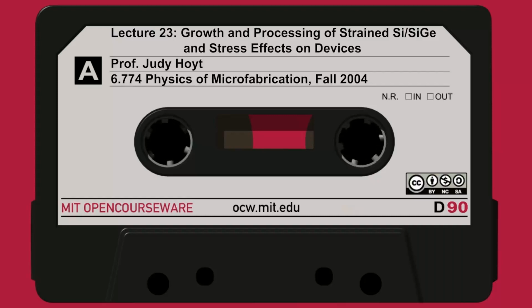Sometimes silicon germanium can also be used as a boron diffusion barrier. We spent a lot of time in this class talking about the fact that boron is a fast diffuser in silicon. That's one of the problems with making shallow junctions. Well, it turns out in silicon germanium, for reasons that are not completely understood, the more germanium you add, the slower the boron diffusion coefficient. So if you put in 20% germanium in the lattice, the boron diffusivity drops by about a factor of 10 in silicon germanium. So that's a huge factor. So people may want to use silicon germanium just as a means of slowing down boron diffusion.